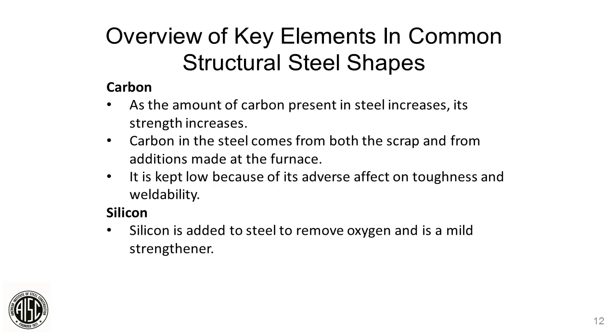Next element that we're going to talk about is silicon. Silicon is a deoxidizer. We add that to take out the oxygen that's present in the liquid steel when we melt it. So it's the primary deoxidizer in structural steels and alloy steels. It has a different use, but we're going to limit our discussion tonight just to structural steels. On the next slide.